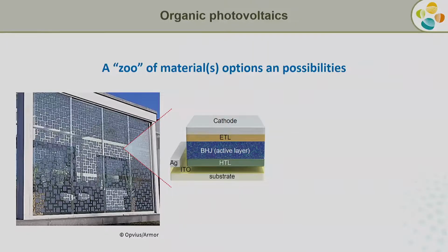So in my group, what we do, we take these technologies, we zoom in, and we isolate this big, nice, interesting design of organic photovoltaic, which are semi-transparent. And if you zoom in, you will see a single photovoltaic cell. What this organic photovoltaic cell usually comprises of is a kind of a multi-layer stack. This thickness is no more than 150 nanometers, very, very thin.